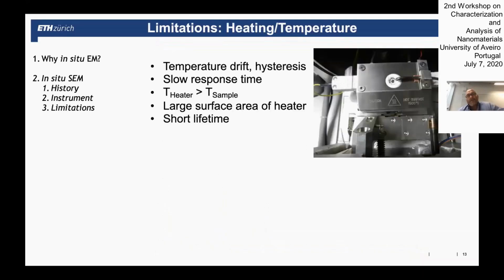Another thing that is not really trivial is when you do heating experiments inside the microscope. You can buy a heater, but then there is always the problem that the heater usually is hotter than your sample. When you cook milk, for example, on a stove, and the stove is hot, heat goes to the pot, and in the pot is the milk. So the milk is colder than the pot, and the pot is colder than your stove. And we did lots of experiments where we were interested in catalysis, but our heater was hotter than the sample. Lots of chemical reactions take place there.